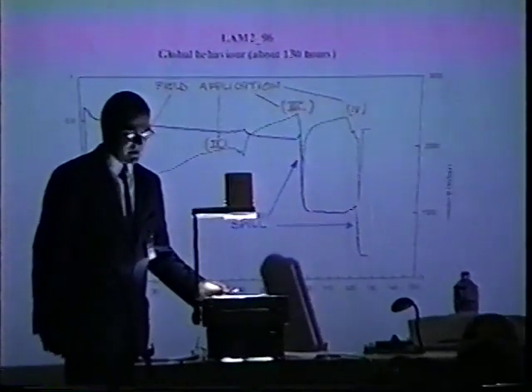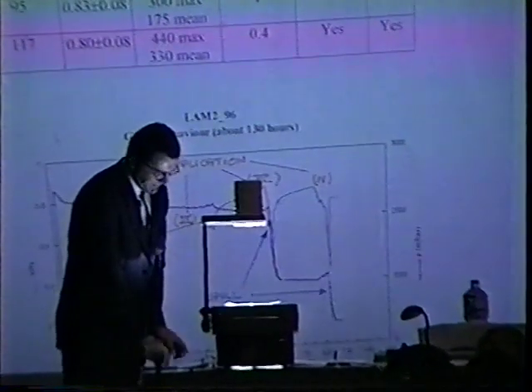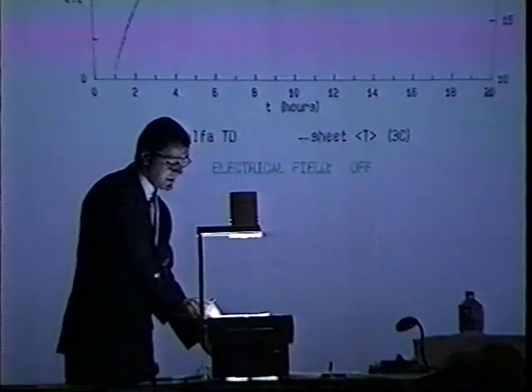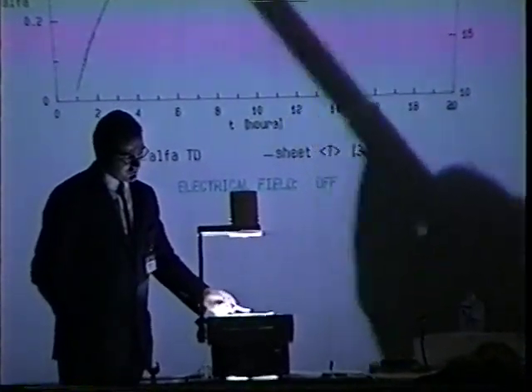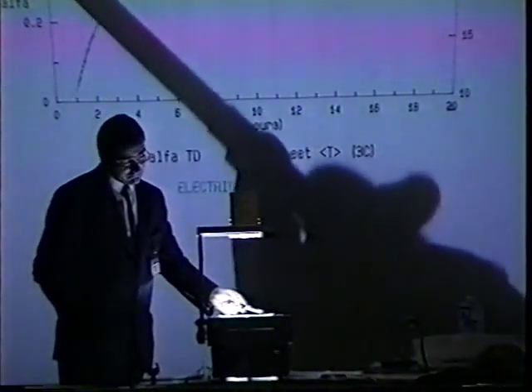On the lower part are the two instants where a spill was performed, to say when some gas was extracted from the cell and subjected to mass spectrometric analysis. So the first 18 hours showed the expected behavior of loading ratio when no electrical field is applied. The characteristics are a first steep region followed by a smoother one leading to the asymptotic behavior, the green curve, while the black curve represents the mean sample temperature during this operation.